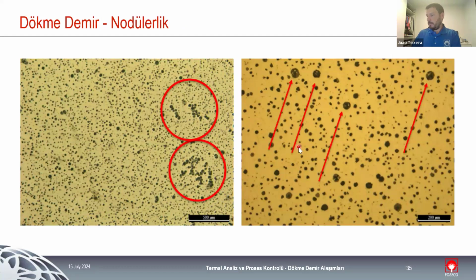And here we can see just some microstructures of nodular cast iron, and you can see, for example, some problems that we already discussed. In these areas, we have a lot of nodules grouped together, so probably we have a really high hypereutectic solidification. So we have a lot of big nodules that grow together, and this could be detrimental for the mechanical properties. And if you look closer, we also can see that we have some problems with the nodules. They are not completely spheroidal, but we had some elements that were probably harmful to the growth of the graphite nodule. So again, we need to be extra careful with everything that we add to the liquid metal, because it can affect the mechanical properties of the cast a lot.